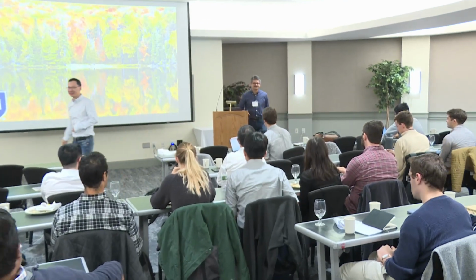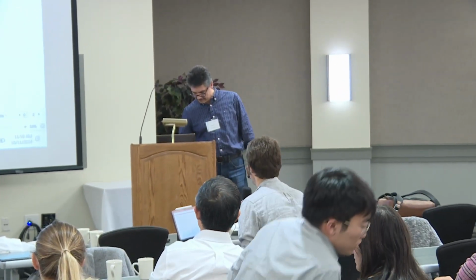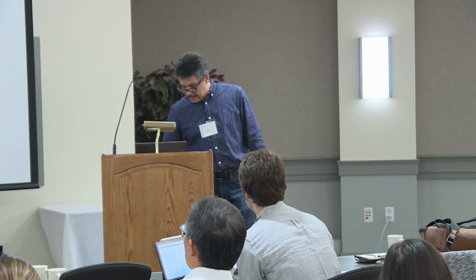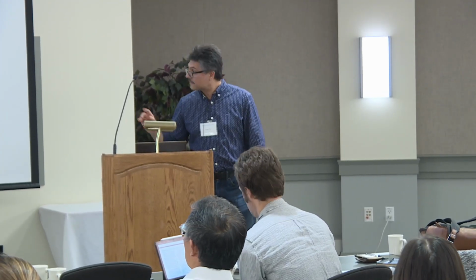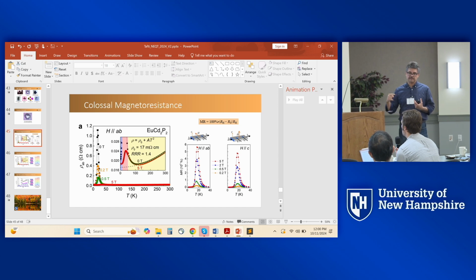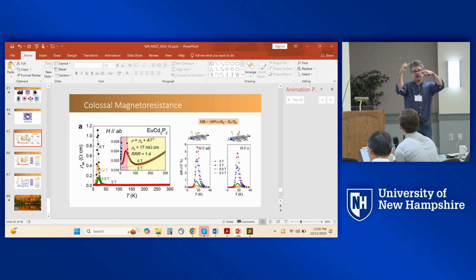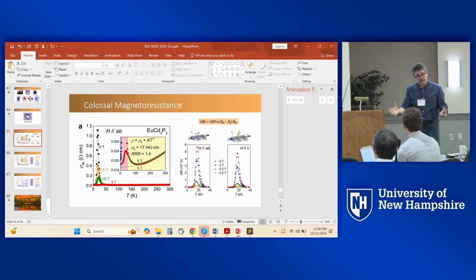I think I have two quick questions. In the last set of materials, do you have any idea what the magnetic susceptibility looks like as a function of temperature? Yes, I don't have the figures here. This is published work. Basically, it looks like an A-type antiferromagnet. When you measure it with the field in the plane, you see a ferromagnetic transition. Out of plane, you see a peak like an antiferromagnet. So spins basically alternate like this. Is it Curie-Weiss-like? It is Curie-Weiss-like, yes. So it's actually fairly localized, in fact.